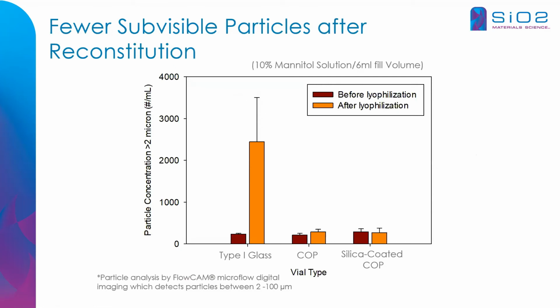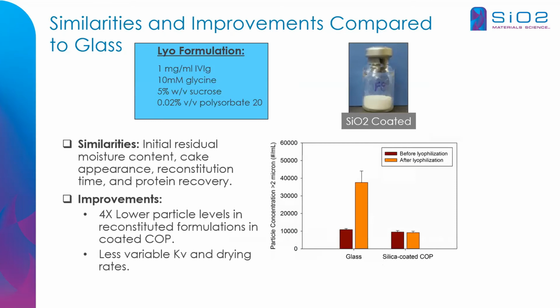Another area that we studied was generation of subvisible particles after lyophilization. And here we are measuring particles in a 10% mannitol solution filled in a 6 ml vial. And what you can see here is a significant increase in subvisible particles greater than 2 micron after lyophilization in a glass vial, and virtually no difference in either an uncoated or standard COP container and a SiO2 or silica coated COP container.